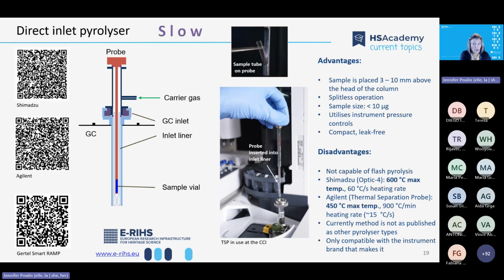It's got some disadvantages. It's not capable of flash pyrolysis, so the Optic 4 by Shimadzu can heat to 600 degrees Celsius maximum at a 60 degrees per second heating rate. The Agilent thermal separation probe, the one that I use, has a 450 degrees maximum temperature, and it heats at a rate of about 15 degrees Celsius per second. Currently, this method isn't as published as other pyrolyzer types, and if I understand correctly, it's only compatible with the instrument brand that makes it.